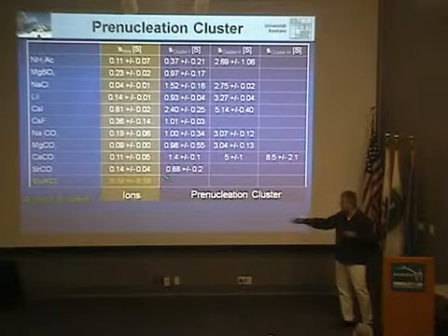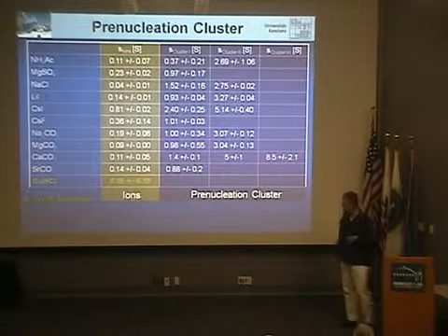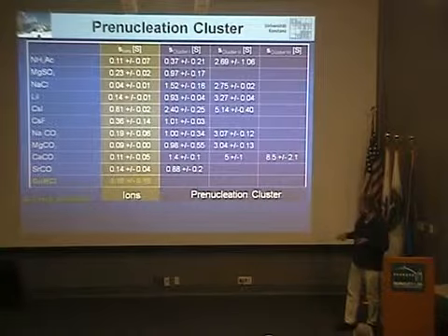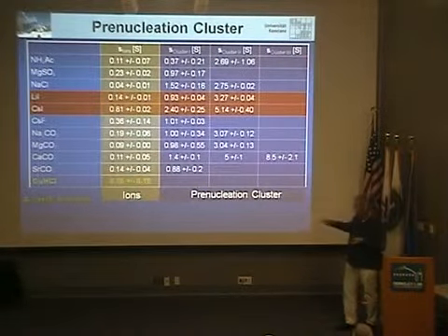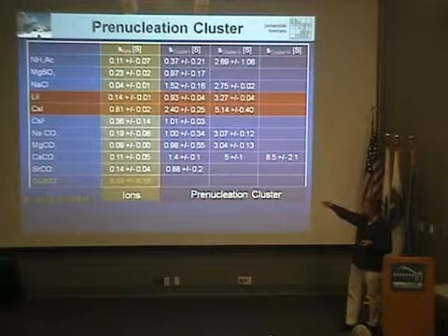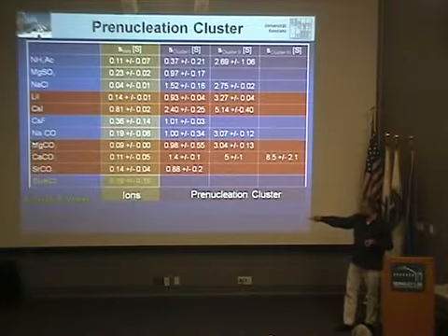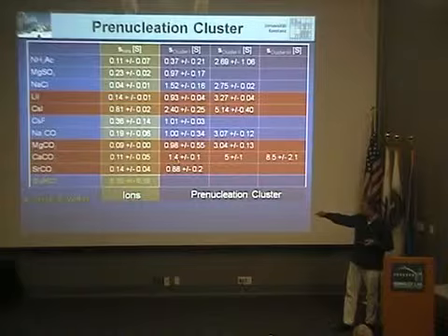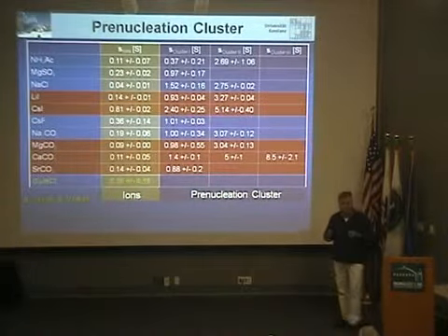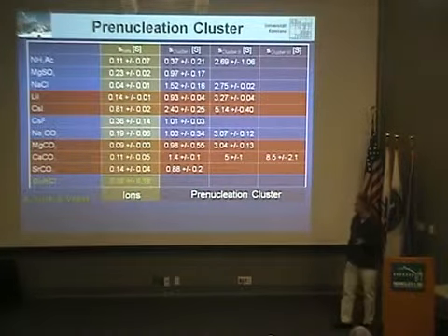The only species where we didn't see clusters so far was guanidinium hydrochloride, a strongly structure or water structure breaking agent. That's the only one which didn't form clusters. And you can also see in a series of, for example, iodides, if I make the cation bigger, going from lithium to cesium, then the clusters also got bigger. But this is no rule. If I take the carbonates, starting from magnesium carbonate, going via calcium to strontium carbonate, first the clusters get bigger, but then smaller again. So it's obviously no rule that the cluster size or sedimentation coefficient scales with the size of the ions.